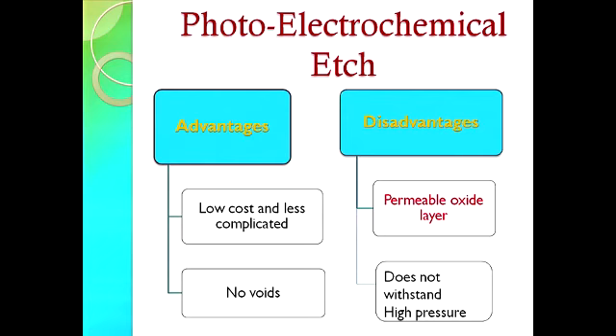So the advantage of photoelectrochemical etch was that it's a low-cost alternative. It's less complicated when compared to the first method, and there were no voids formed because of the type of etching that we used. But the disadvantage is that it forms a permeable oxide layer, which cannot withstand high pressure or shear stress when compared to the previous method.